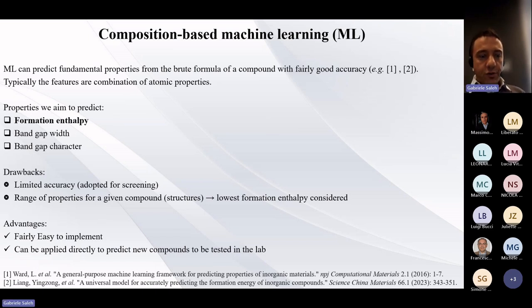The drawback of using only the composition is that the accuracy is obviously limited, but we are interested in a screening tool that only gives us the good candidates to be tested in the lab or to be tested by further simulation, so it's good for us. And some properties are not unique for the composition, so one can have polymorphs. We overcome this by taking for each composition only the lowest energy structure.